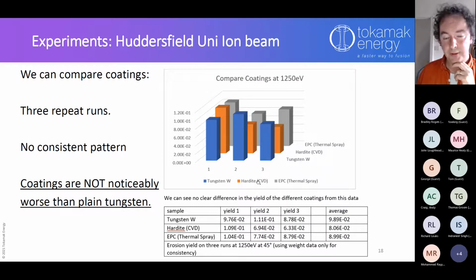We can compare the different coatings. This is run 1, run 2, and run 3, and the blue columns here are the sputter erosion yield under identical conditions. You'll see they're actually not very consistent at all. It goes up by about 20% and then it drops by about 10% from the first run. The other coatings are similarly up and down all over the place. So this shows that there's considerable error and reproducibility issues from one run to the next. However, when we average the whole lot, we find that the sputter yield between these different coatings on average is pretty close. And we can say they're not noticeably worse than tungsten.